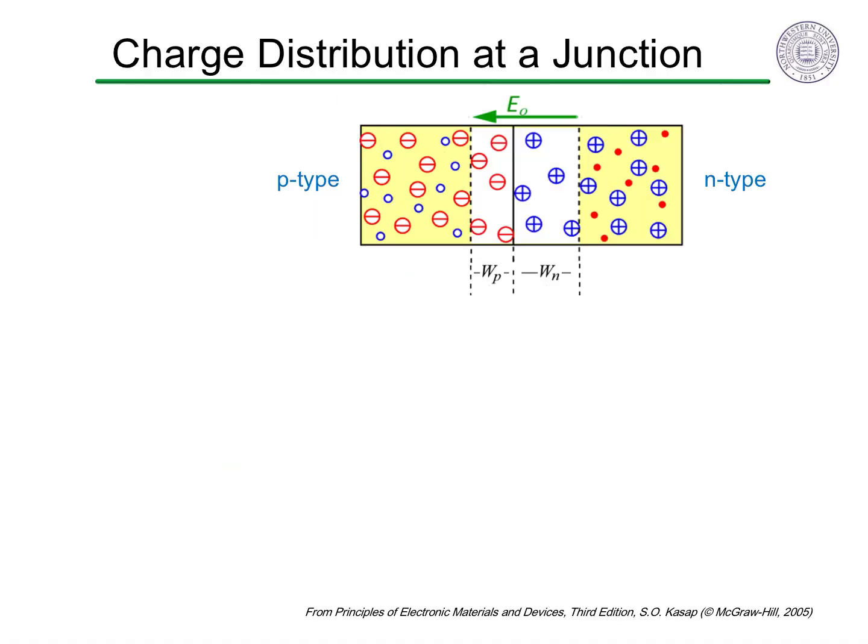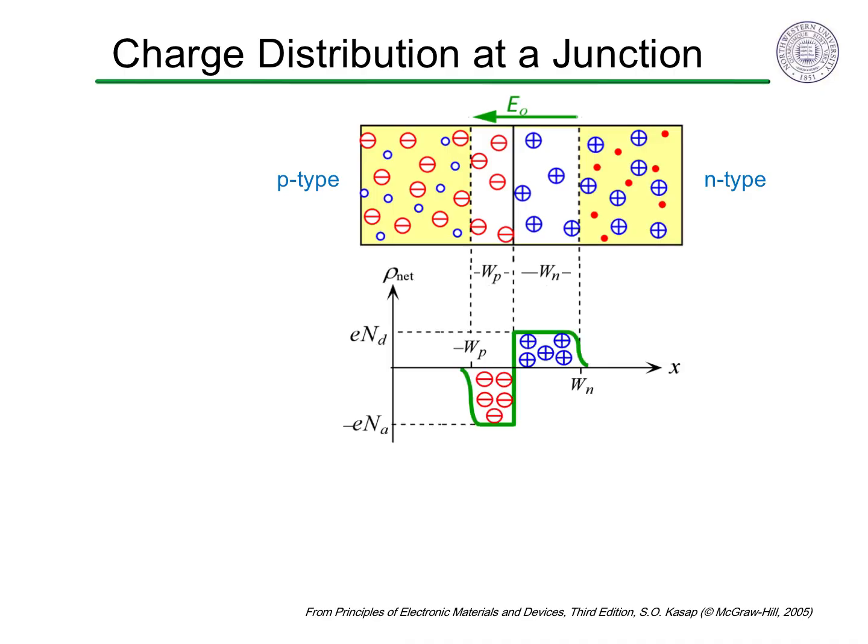When all the holes in the p-type region are depleted, the concentration of excess charge is the acceptor dopant concentration. We can approximate that this persists for a length we will call the depletion width into the p-type region, W sub p. Similarly, the n-type side has a charge density of approximately the donor dopant concentration with depletion width W sub n. Here we sketch the excess charge in the system.